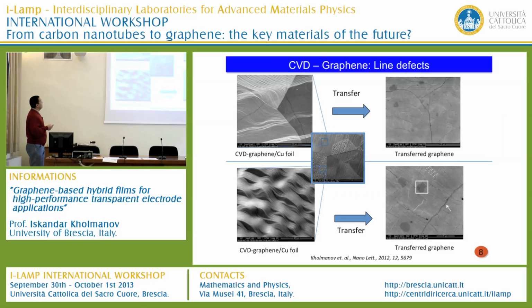Another type of defects are line defects. This is CVD grown graphene on the original copper foil. First of all, the black lines here are wrinkles in the graphene on the copper foil. These arise due to the different thermal expansion of the graphene and the copper substrate. These wrinkles form during the growth process, and when you transfer the graphene from the copper foil onto the target substrate, these defects are maintained. So you cannot remove this kind of line defects. Moreover, the copper substrate is not perfectly flat.